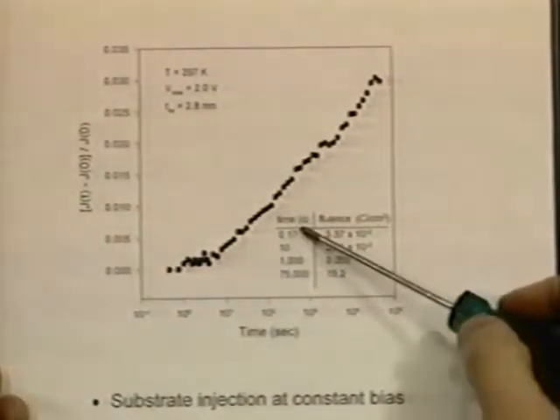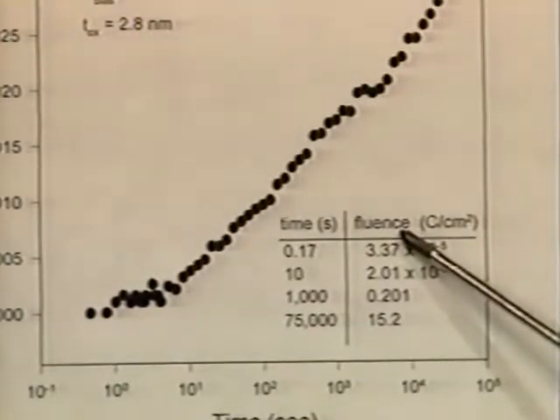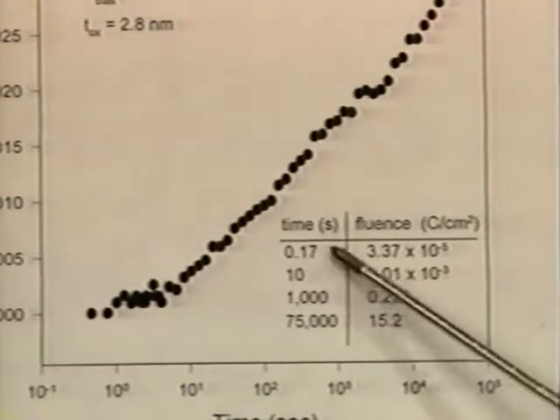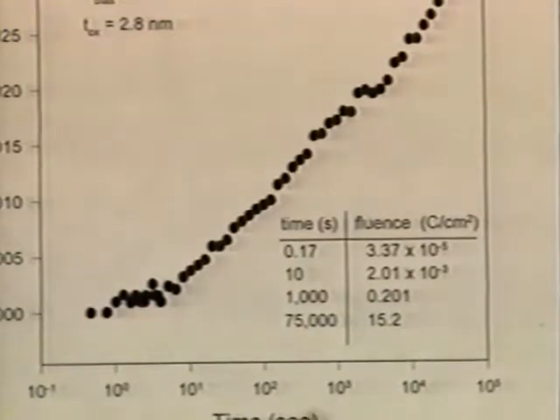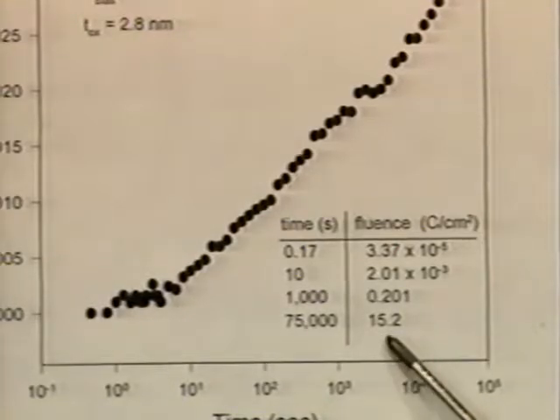And I don't know if you can see this on the screen or not, but what I've put here is the time and the corresponding amount of fluence, or the number of electrons that have passed through the device. Like 0.17 seconds, there's about 10 to the minus fifth coulombs per square centimeter. Not much fluence. But after 75,000 seconds, there's a tremendous fluence that's passed through, 15.2 coulombs per square centimeter.